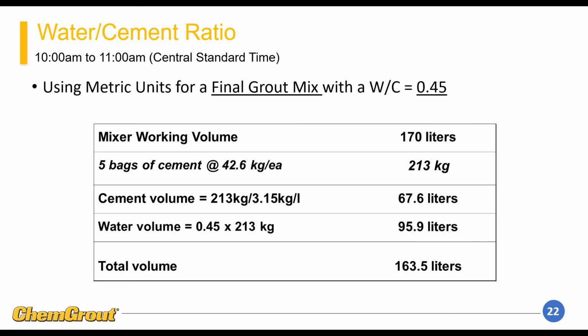Then the other mix that we use in hollow bar grouting is the final mix, which is the structural grout, which has that water to cement ratio of 0.45, which is typically about five bags of cement to about 25 gallons of water.